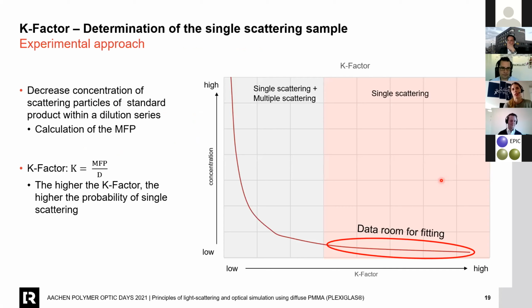So how can we get the single scattering data? To determine the single scattering experimentally, we need special samples with very low concentration. Our standard products have higher concentrations of scattering particles, so multiple scattering is the main effect, and it's not usable for this approach. So we have to decrease the concentration of scattering particles and determine the mean free path for each sample. Depending on the sample thickness, we introduce a new parameter, the K factor. The K factor is the ratio of the mean free path and the sample thickness, and the higher the K factor, the higher the probability of single scattering.